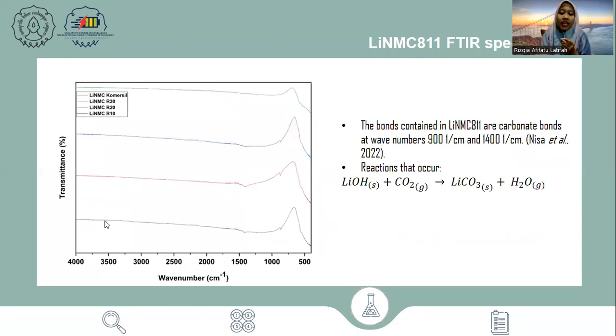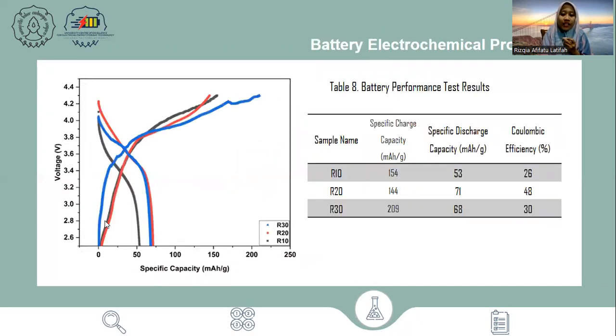And then lithium nickel manganese cobalt material was also tested using Fourier transform infrared spectroscopy. There are carbonate bonds in the wave numbers 900 and 1400. This is due to lithium hydroxide, which is easily changed to lithium carbonate due to the presence of carbon dioxide in the air. Then the electrochemical properties of the battery.